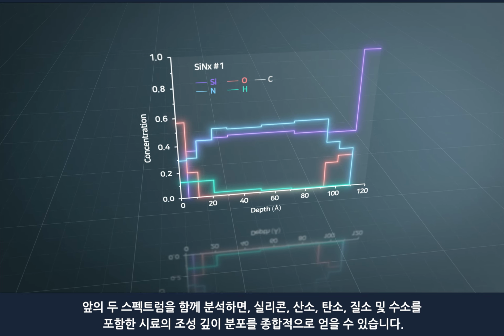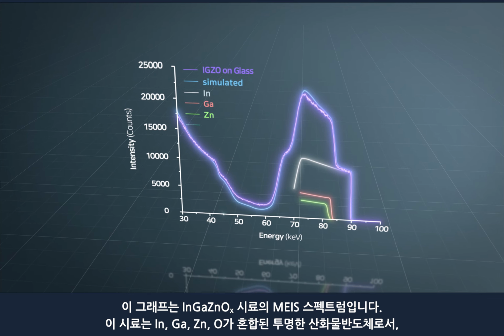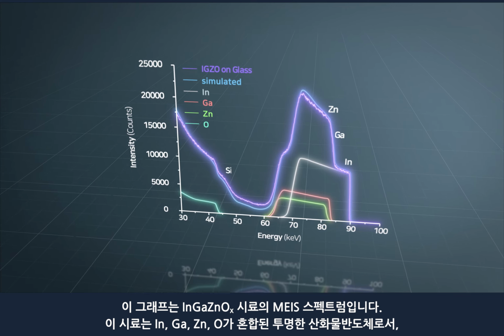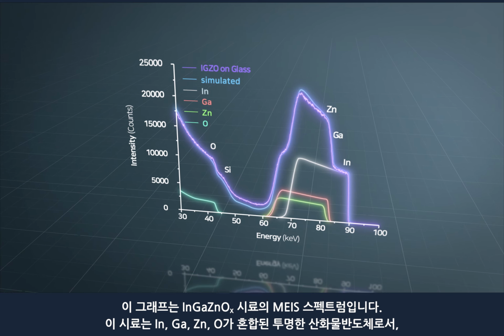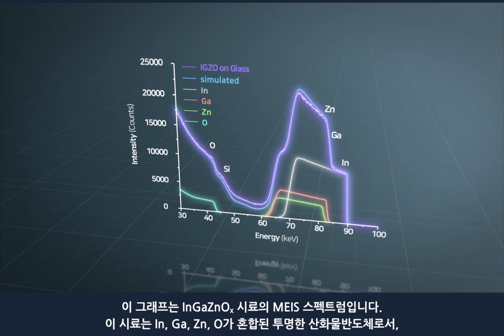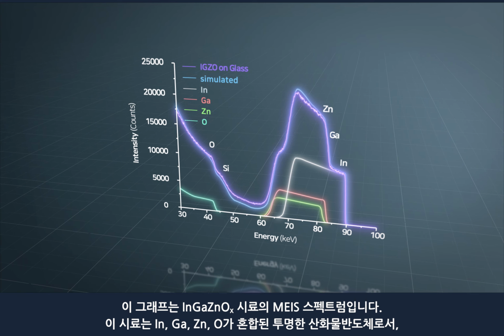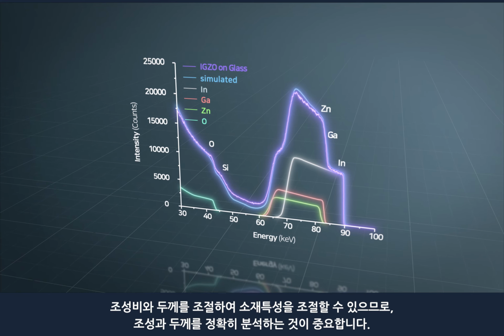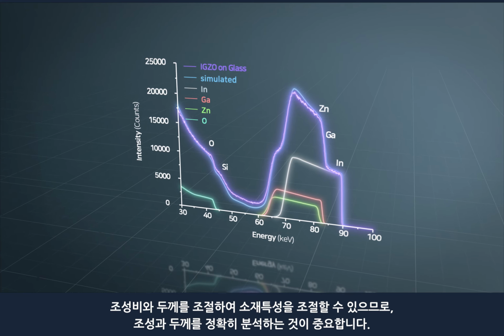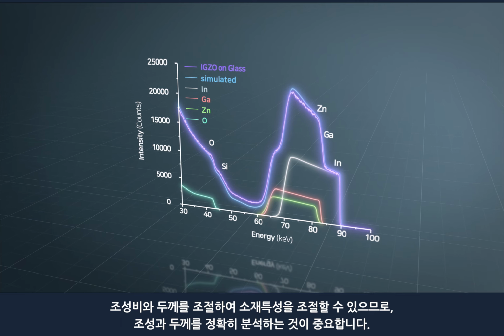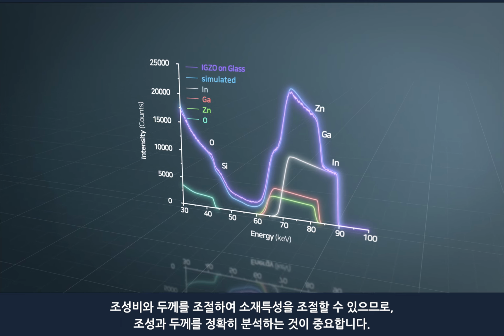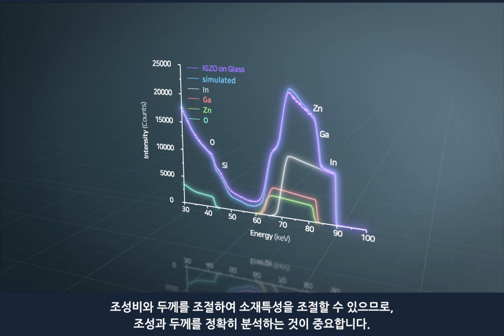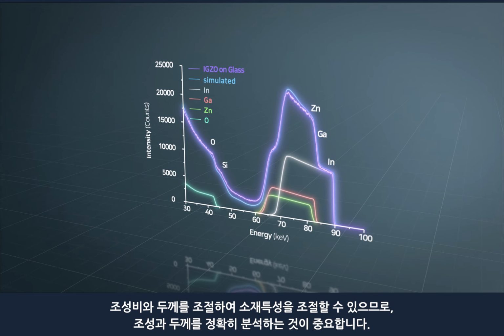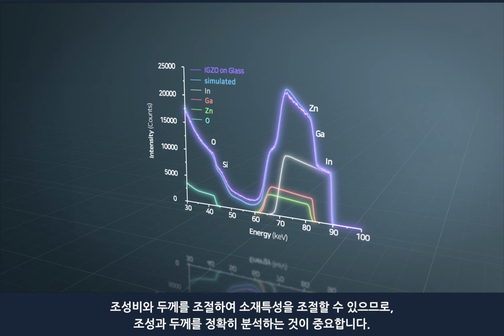This graph shows the MEIS spectrum of the indium gallium zinc oxide sample, called IGZO for short. It is a transparent oxide material comprising indium, gallium, zinc, and oxygen. The properties of IGZO can be modified by adjusting its composition and thickness. Therefore, an accurate analysis of the composition and thickness is important and can be achieved using MEIS measurements.